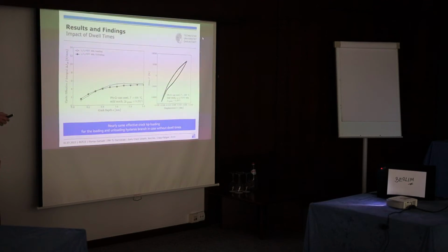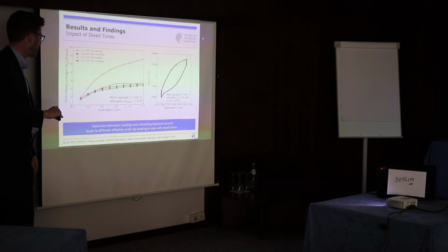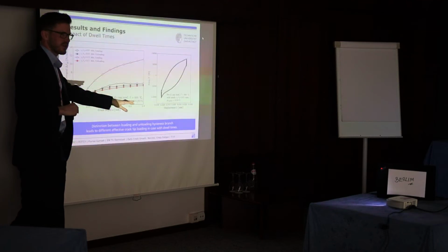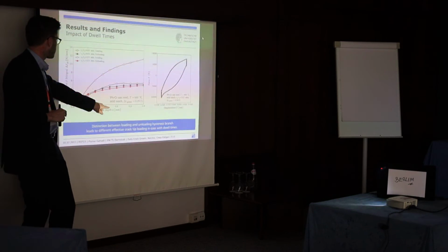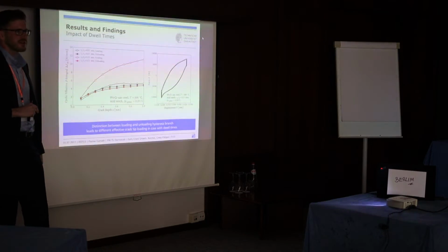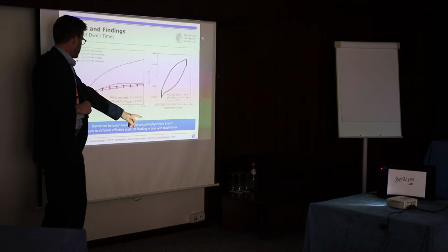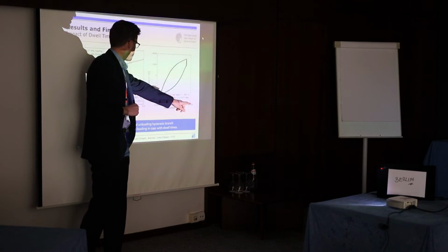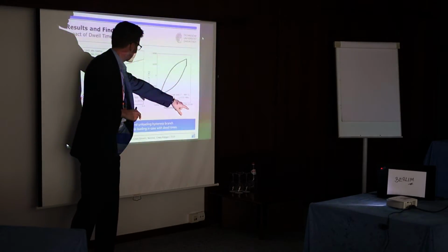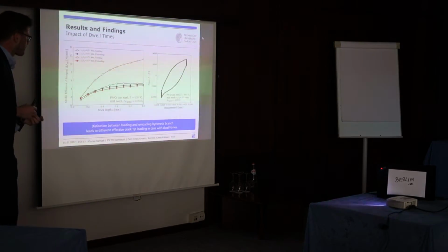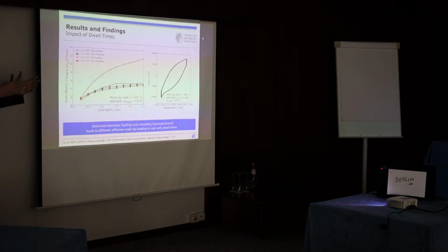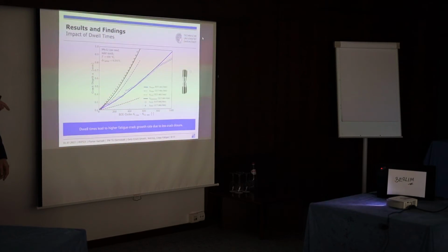So for fatigue loading, everything is fine. We end up with the same results for loading and unloading. But what happens now if we add the dwell times of 3 minutes in tension and compression, we end up with a huge difference in crack tip loading. You see here for the loading part of the hysteresis, we get much higher delta J effective values. And this is already shown here in our experimental measurements. You see a kink in the unloading branch indicating crack closure, but you can't see a kink in the upper branch indicating crack opening. So this tells us the crack is already open here during this dwell time in compression due to relaxation. And this is a very important finding, which enabled us to pretty good describe the crack growth.